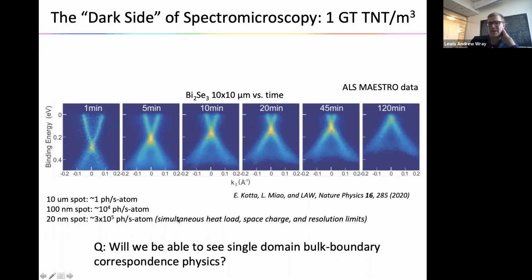But empirically this has been characterized. The effective heat load has been characterized quite well. It's basically just an energy density, but other factors as far as whether or not you can perform a measurement include whether you're charging the sample and whether you're getting a space charge, which is too many electrons coming out at the same time in a small space, so they repel one another and ruin your resolution.